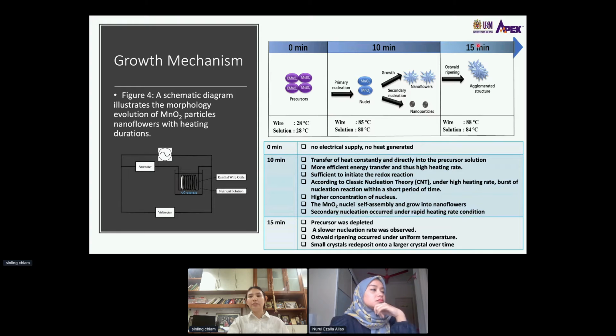By prolonging the reaction to 15 minutes, most of the precursor was depleted, so a slower nucleation rate was observed. However, under uniform heating temperature, Ostwald ripening tends to occur, where the small crystals redeposit onto larger crystals over time. Therefore, we observe an agglomerated structure at the longer time.